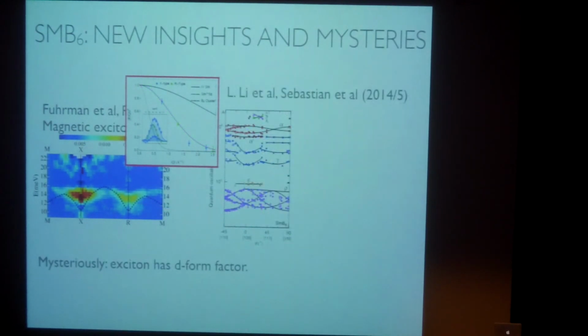And even more mysterious, de Haas-van Alphen shows 2 kinds of signal. Something that looks like a surface signal, which Lu Li and his collaborators have detected, and more recently, more accurate measurements have revealed the presence of also bulk oscillations, which may be due to magnetic breakdown, but maybe because there's something weird going on in the bulk. It's then a strange insulator.